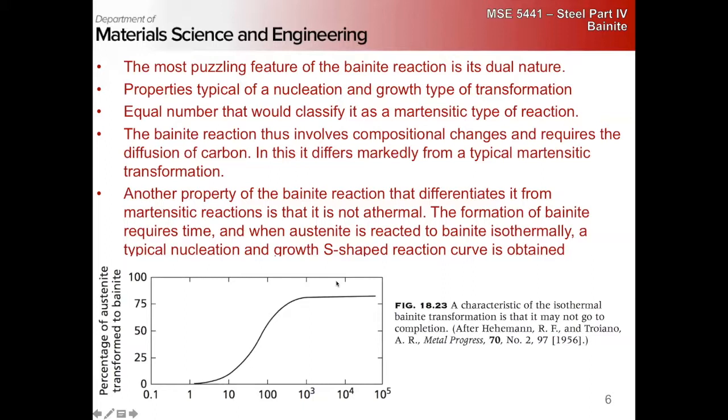But the formation of bainite requires an incubation time, right? And when we hold it isothermally, we get a typical nucleation and growth curve. But notice it doesn't go to completion. It goes to a value that depends on the cooling. So if I were to lower it down, I have martensite, I have a bainite start and a bainite stop temperature.